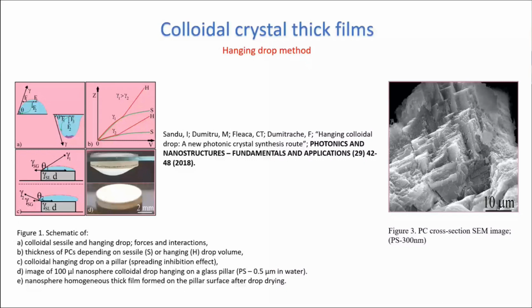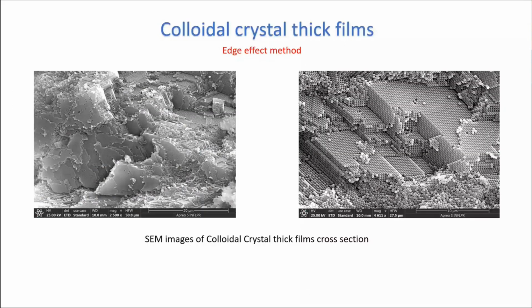Here is an example and the methods for obtaining thick colloidal crystals. Inside of such crystals you can see the degree of organization. In fact, we do not have a single crystal, but rather a polycrystalline material. And depending on the method, we have larger or smaller single-domain sizes.